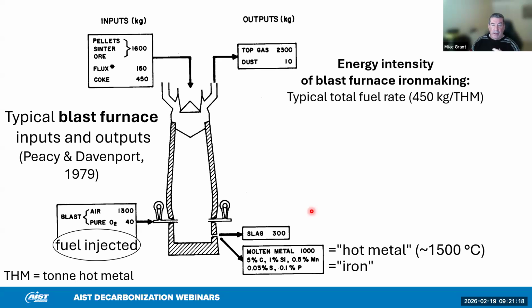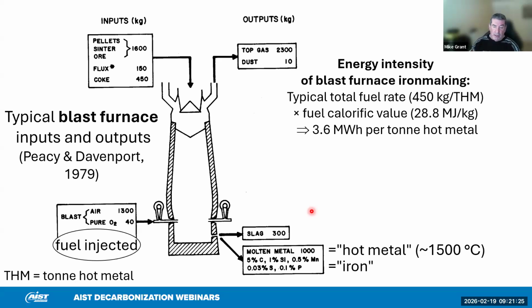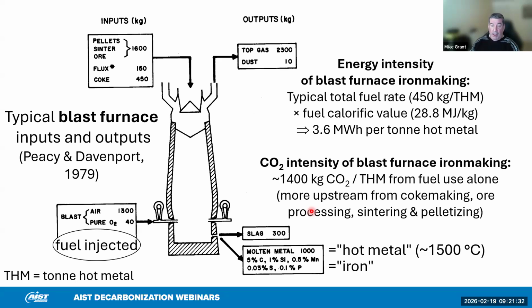The energy consumption of the overall blast furnace process is about 3.6 megawatt hours per ton of hot metal. And the CO2 intensity, so this process emits 1,400, 1,500 kilograms of CO2 per ton of liquid pig iron that is produced, that is tapped out of the furnace. And therefore, the blast furnace produces actually more mass of CO2 than it does iron. Iron is the product, of course, we want to process into steel, and we're actually making more CO2 than we are iron. The hot metal comes out at about 1,500 degrees C, along with a slag, which captures many of the impurities like sulfur and other things.